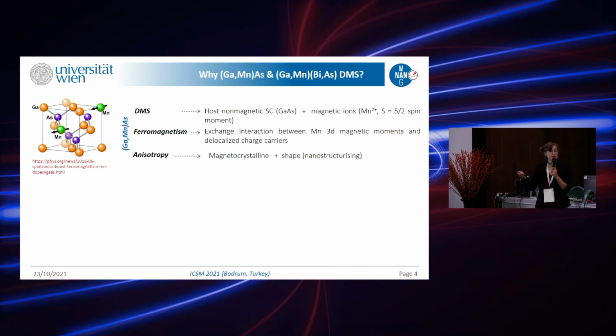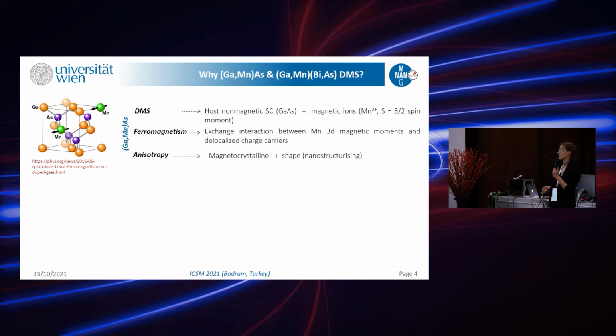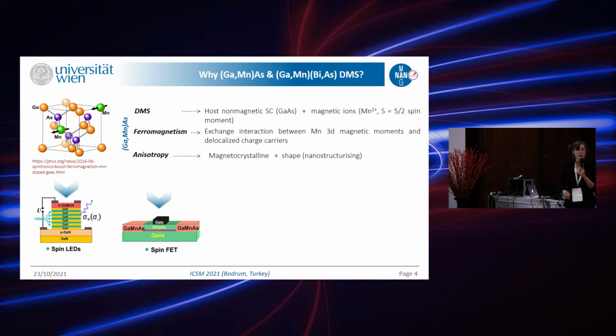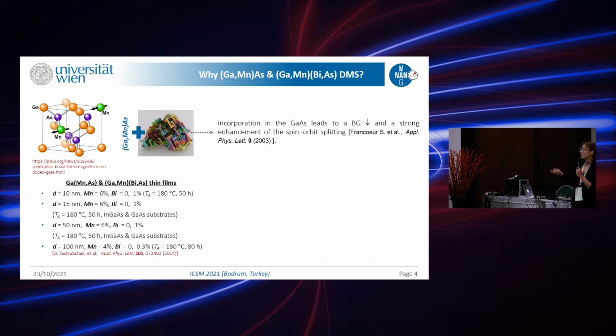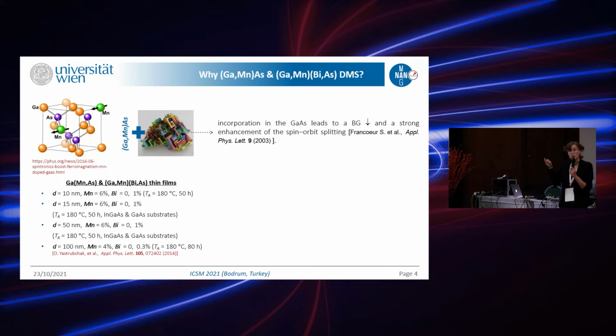But what if we add manganese to this? We will get a dilute magnetic semiconductor, gallium manganese arsenide. It's a ferromagnet where the exchange interaction is driven by the interaction of manganese 3d moments and delocalized charge carriers. It's an interesting material, and there are already a lot of different concept devices created with it. But we decided to go even further, as the material was booming in investigations in the mid-90s. And this is a novel thing: we added one of the heaviest stable elements of the fifth group, which is bismuth.